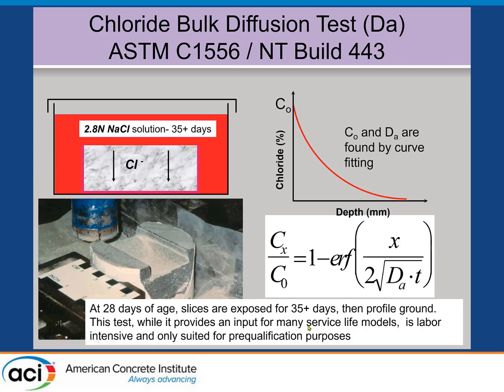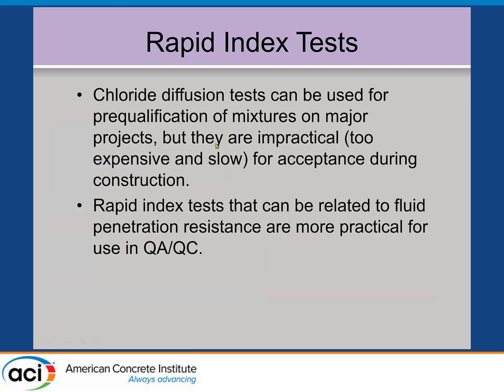However, this is a very labor-intensive test method. It may be suitable if you have lots of time in advance of a project for pre-qualification purposes on major projects, but it's really not suited for acceptance. So for acceptance, we need rapid test methods. And test methods to be rapid are typically index methods. They don't provide a direct value that maybe could be used in service life models, but they're index methods. They give you an indication of that fluid penetration resistance. So they're more practical and potentially usable for QA/QC purposes.